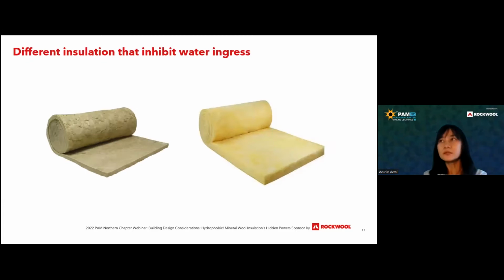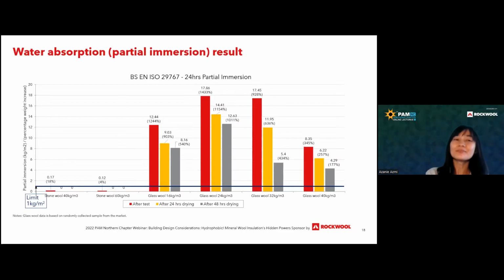So talking of the test methods, we want to see the differences in performance of different mineral insulation. So we subject two different mineral insulations to a series of water absorption tests to see which one is better as well as which one is the worst. So here are the results. What you see here is the partial immersion test, ISO 29767. There are 6 samples: Stonewool 40 kg as well as 60 kg, and Glasswool 16 kg, 24, 32, and 40 kg.